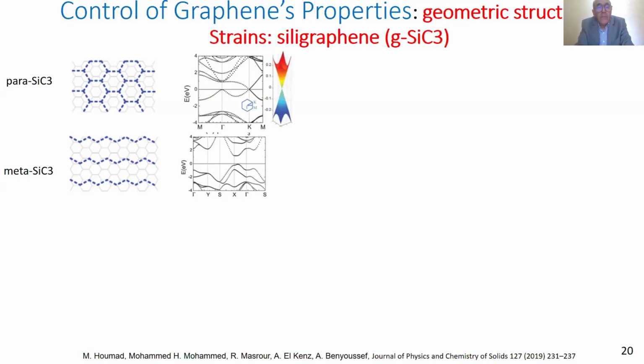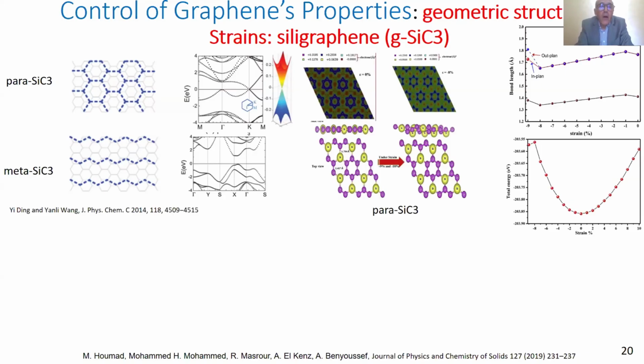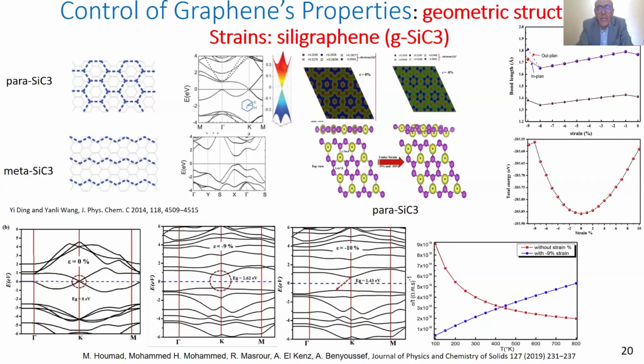Semi-metal with a Dirac cone with linear dispersion energy, and the second one is semiconductor with a direct band gap. But we can modify this property by strain. And by making strain on this para-silicon carbide, we can see a decrease of stability of the materials with increasing the strain, and also a change of the lattice parameter. And this gives transition from a semi-metal to a direct semiconductor